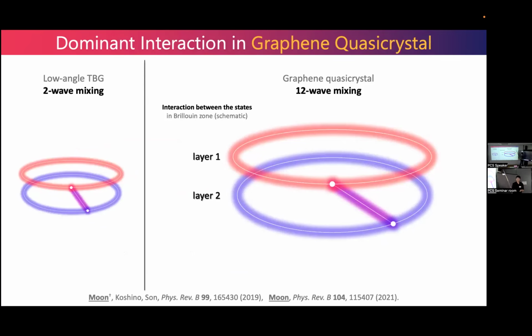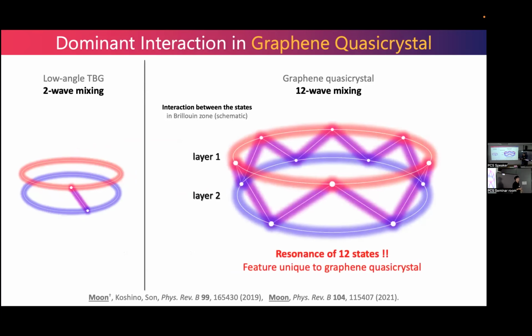In a quasicrystal configuration, however, a single state in layer 1 is degenerate with 2 states in another layer at the same time. And these states also interact with these 2 states. And finally, 12 degenerate states make a closed-loop interaction. That is the origin of the resonant interaction. And this is possible only in the quasicrystalline configuration.